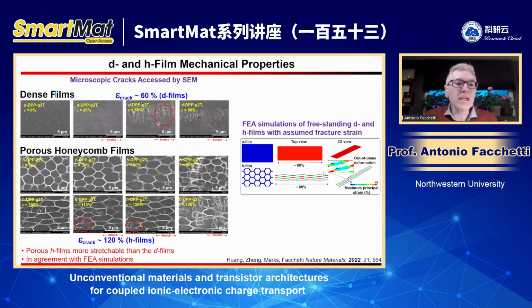So we made this film dense or porous on elastomer, and then we start stretching them. Here we stretch it in this direction. You see here that for the dense film, at about 60% you form cracks. And instead for the honeycomb film, the first crack starts on the order of 100 to 120%. So indeed, having this honeycomb structure helps the mechanical deformation.